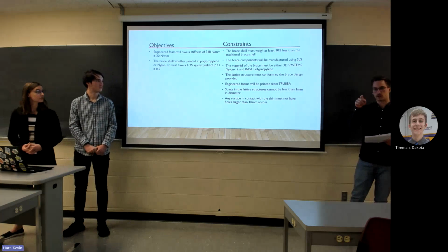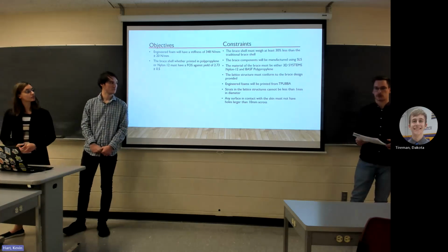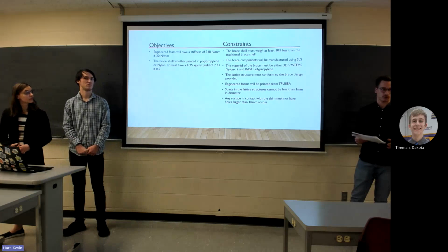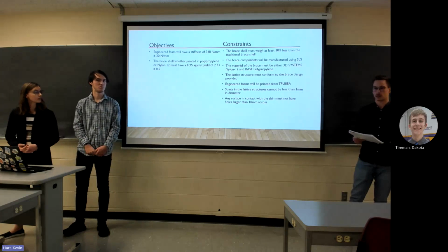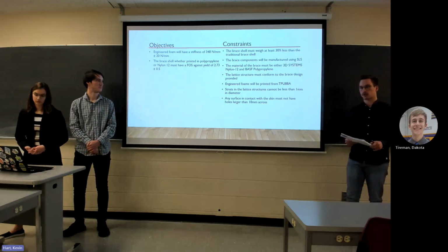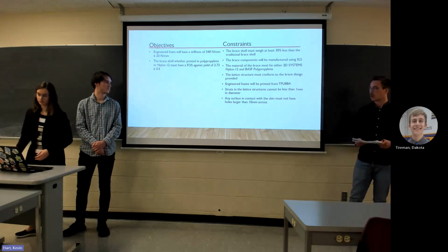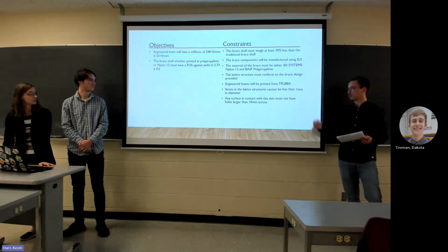So the strut size of each cell can't be thinner than 1 millimeter. This is constrained by the additive manufacturing, so we can't print geometries less than 1 millimeter thickness. So we have to have at least 1 millimeter.